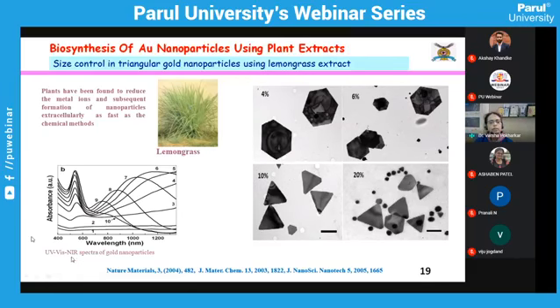So this is the UV visible spectra of the gold nanoparticles, and here you can see that depending upon the size, the percentage of the extract that is being used, from 4% to 6% to 10% to 20%, how the change in the size and the shape of the nanoparticle has occurred. And you can see why I have shown particularly lemongrass, because this is known to give very nice triangular shaped or prism shaped gold nanoparticles. So size control can easily be obtained just by having a control over the percentage of the extract that is being used.